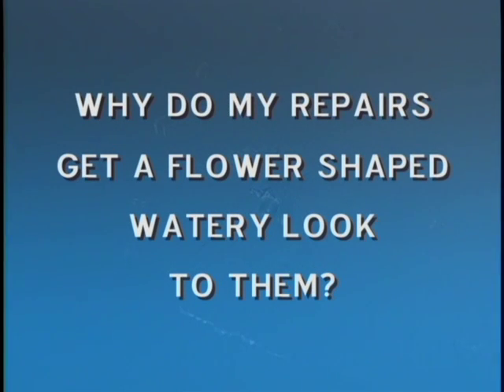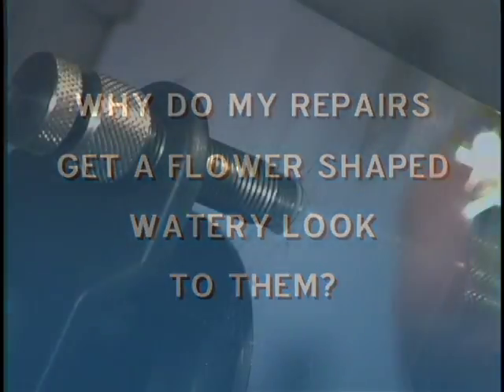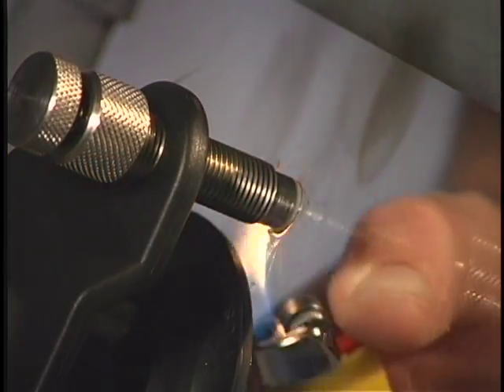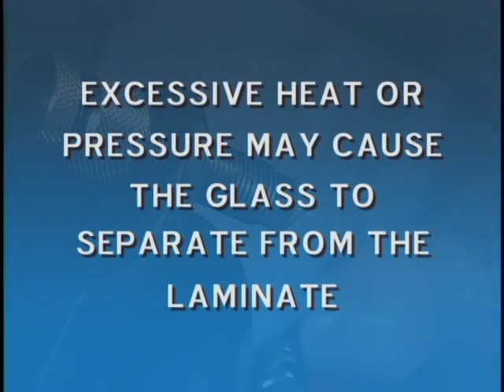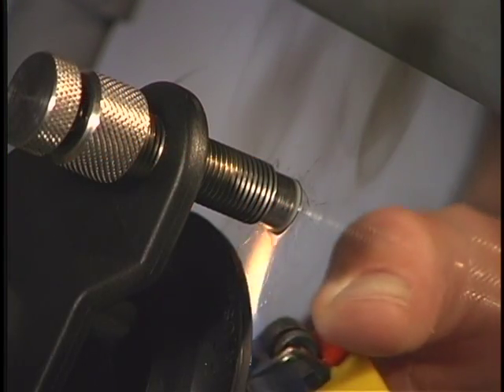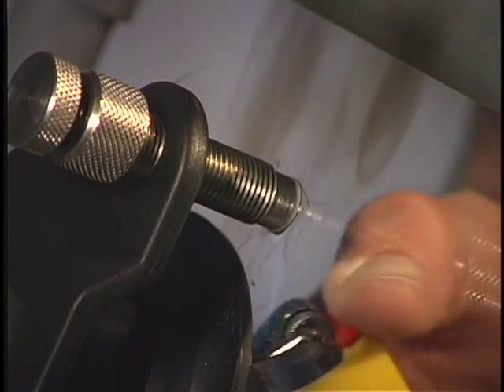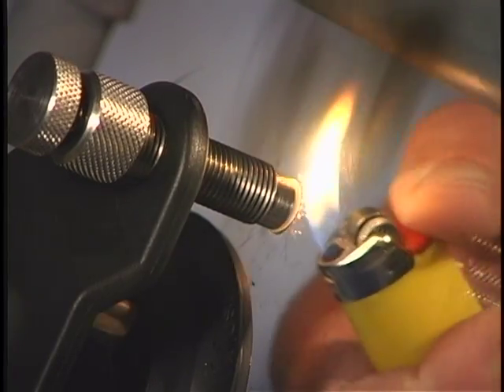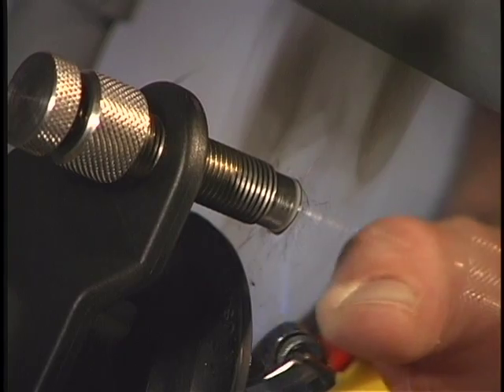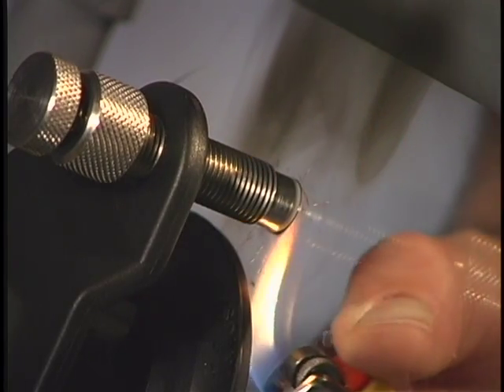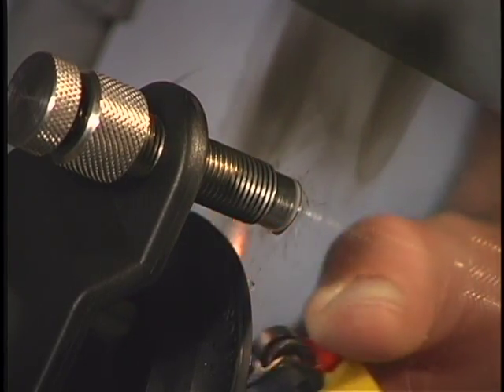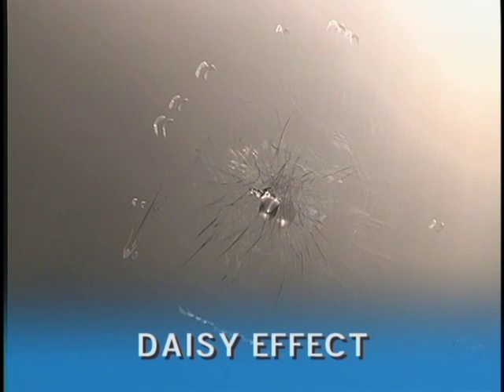Why do my repairs sometimes get a flower-shaped, watery look to them? Excessive heat or pressure may cause the glass to separate from the laminate, allowing the resin to flow out past the border of the original damaged area. This problem is most common in very hot climates and in breaks such as bullseyes and large combination breaks, but may also occur at the end of a crack. Sometimes called the daisy effect, it is not a structural problem, but can be visually unappealing.